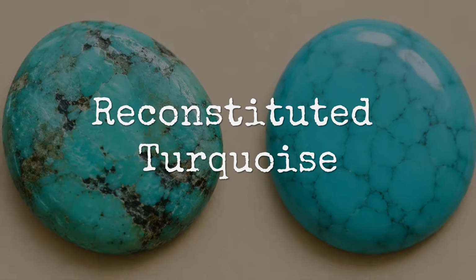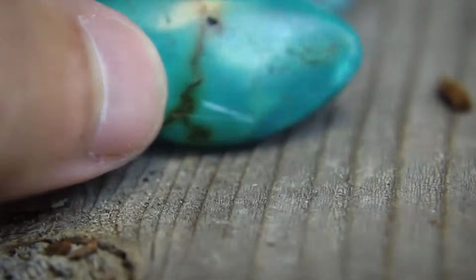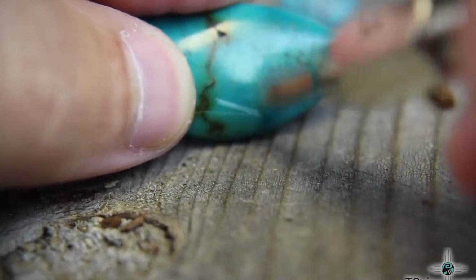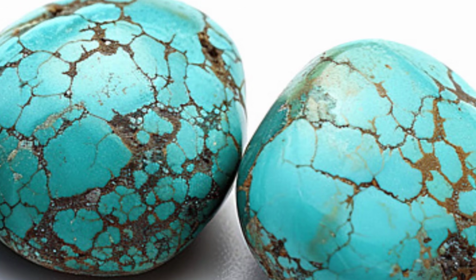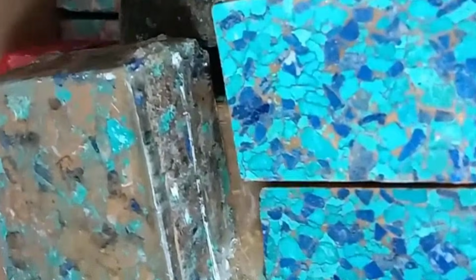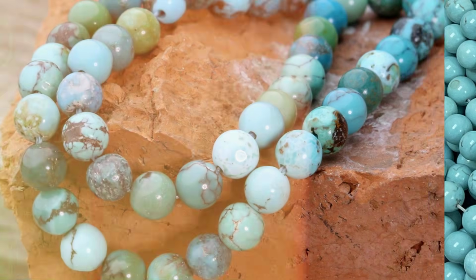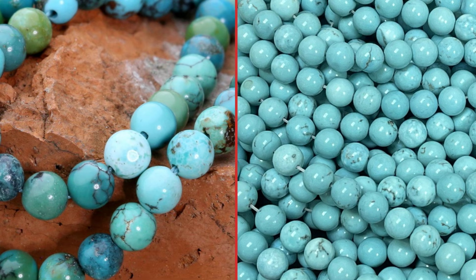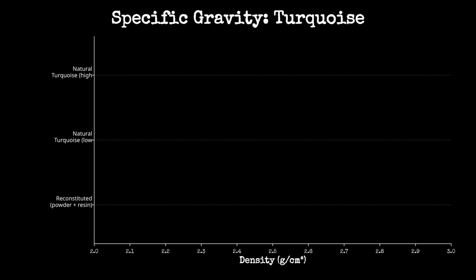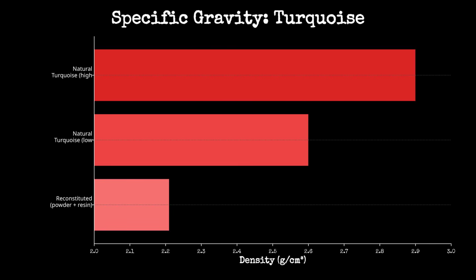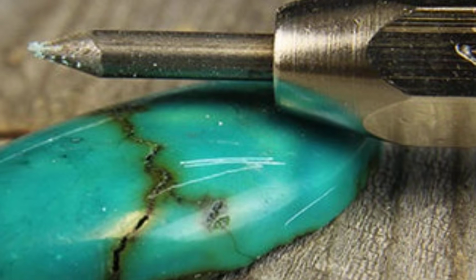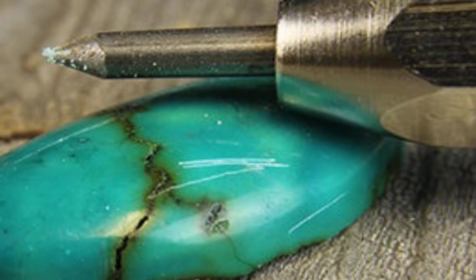Reconstituted turquoise. Genuine turquoise is porous, soft on the Mohs scale, 5 to 6, and often too fragile for jewelry without stabilization. So dealers grind it into powder, sometimes mixing in howlite or straight plastic filler, blend it with resin, and compress it into blocks. The result has too perfect color uniformity, no natural matrix variation, and a specific gravity as low as 2.21 compared to natural turquoise's 2.6 to 2.9.